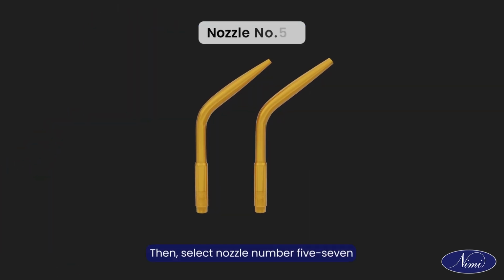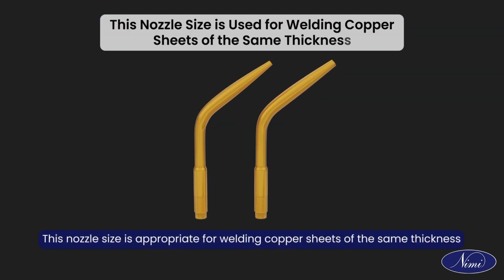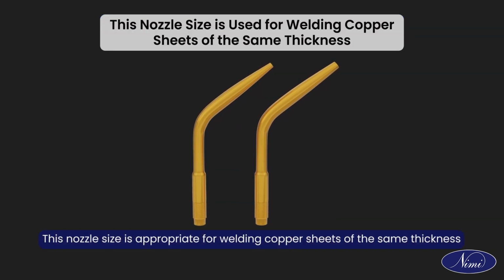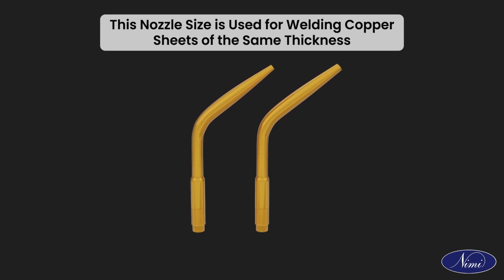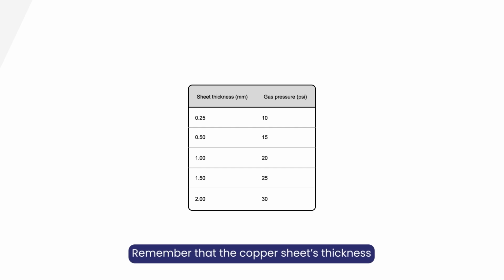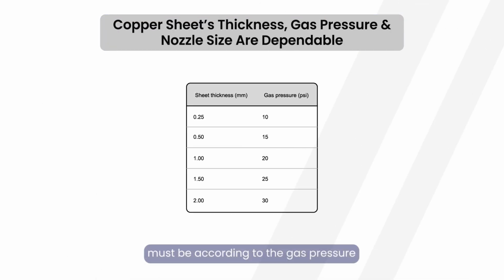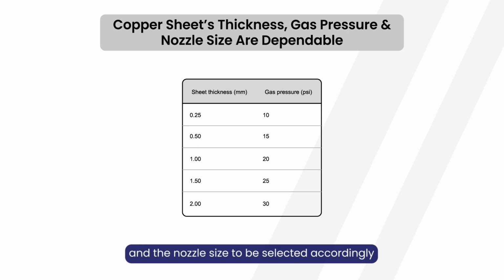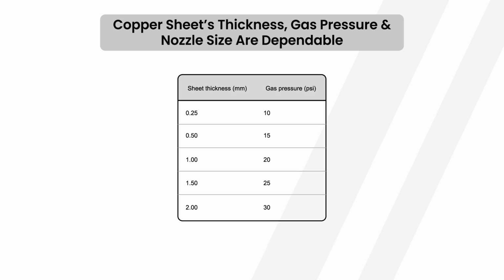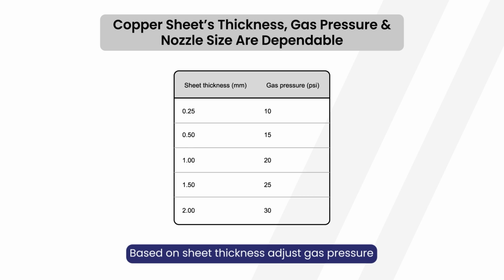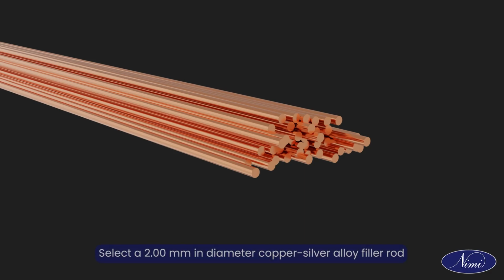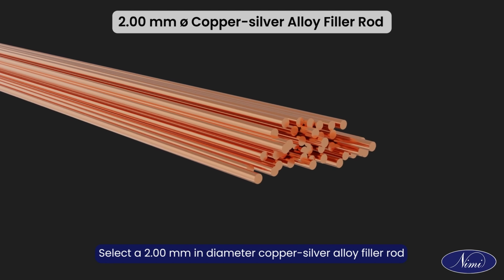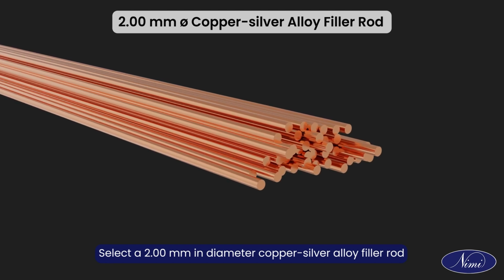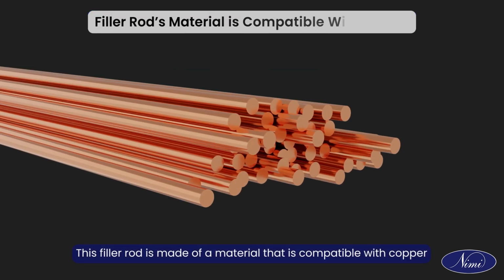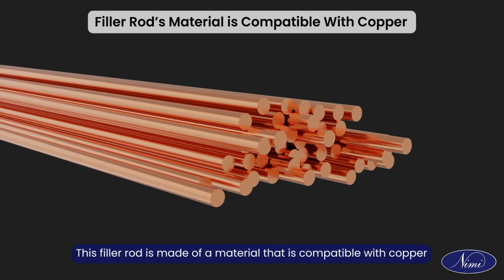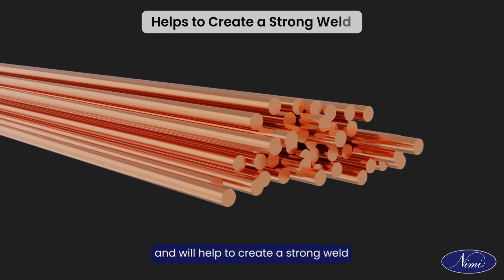Then, select nozzle number 57. This nozzle size is appropriate for welding copper sheets of the same thickness. Remember that the copper sheet's thickness must be according to the gas pressure and the nozzle size to be selected accordingly. Based on sheet thickness, adjust gas pressure. Select a 2.00 mm in diameter copper silver alloy filler rod. This filler rod is made of a material that is compatible with copper and will help to create a strong weld.